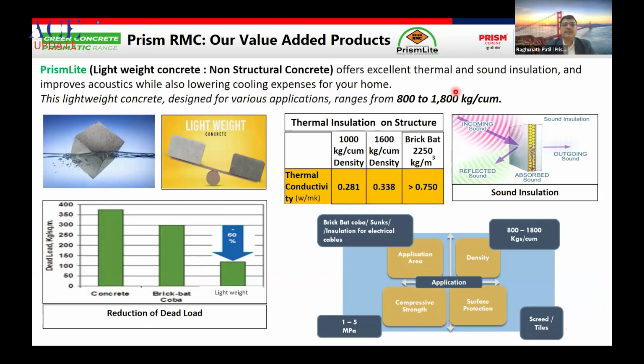The density of concrete is not fixed. Actually, the density of concrete depends on the ingredients we use, and it comes around 2400 to 2500 kg per cubic meter. But in some cases, we replace the natural aggregates with artificial aggregates, and we make the concrete lighter. So the density of concrete is around 800 to 1800 kg per cubic meter, and we replace the coarse aggregate with EPS beads of 2 to 3 mm, and we make the concrete very light. So these are some of the advantages.